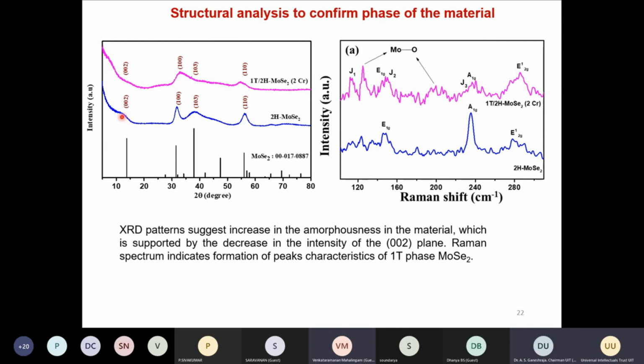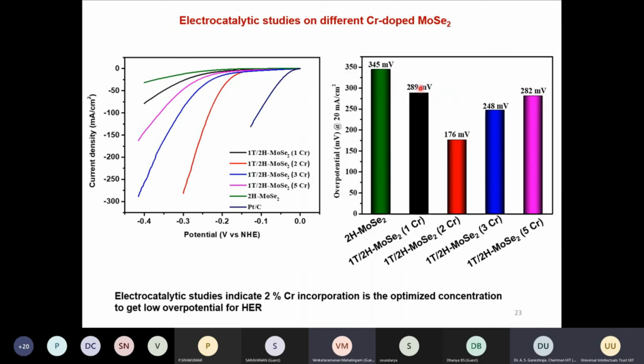And here you see the peak for the 002 plane, which gives an idea of the interlayer distance. Here again, you can see that for the 1T phase we have more peaks compared to the 2H phase, but 1T is present along with the 2H phase. So as I mentioned before, it is very difficult to prepare a pure 1T phase. It's still a challenging one. So here I show the result. Here I have given the platinum carbon for comparison. So basically you need to reach this.